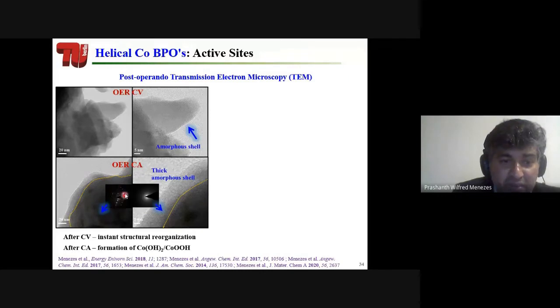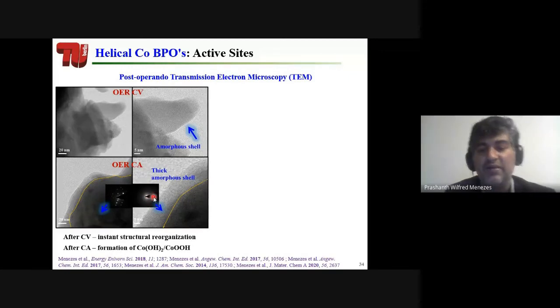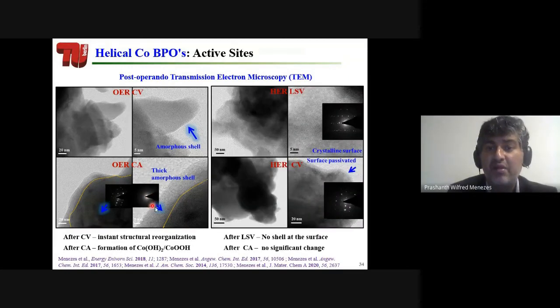This is the electron diffraction pattern. This is similar to X-ray diffraction. When you have such spots, that means that your material is crystalline. And when you have no diffraction pattern, there is no spot, that means your material is amorphous. Okay. And similarly, we checked after hydrogen evolution reaction, we have the same surface passivation, but in this case, we have a lot of reflections. That means our crystalline material is still crystalline. It didn't form amorphous shell as we could see here under oxygen evolution reaction.